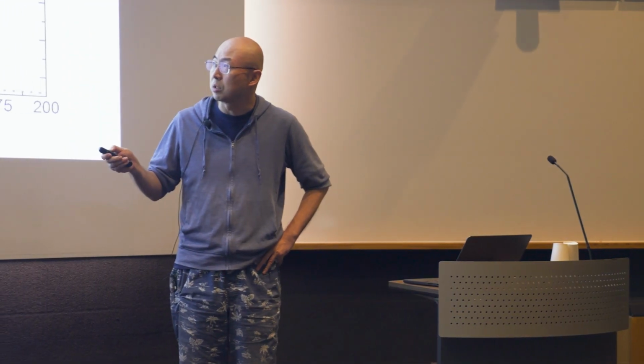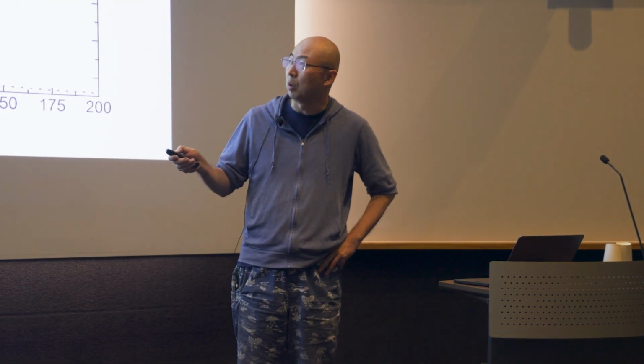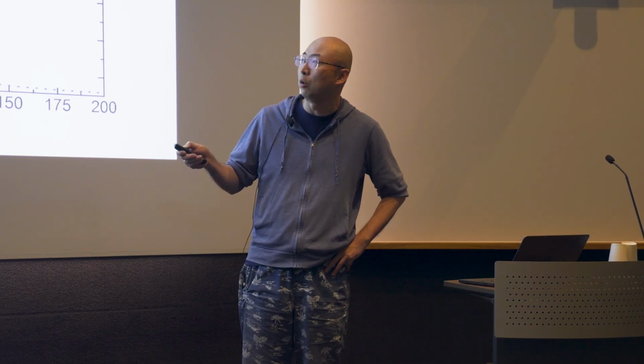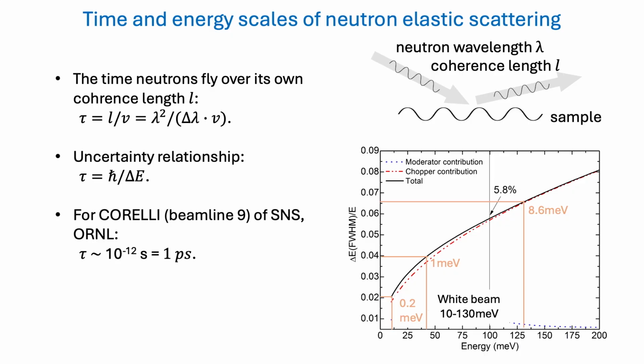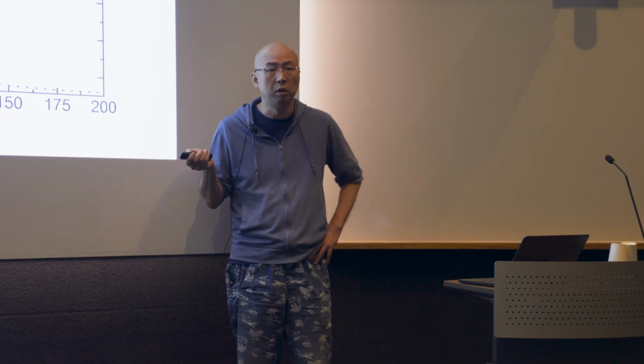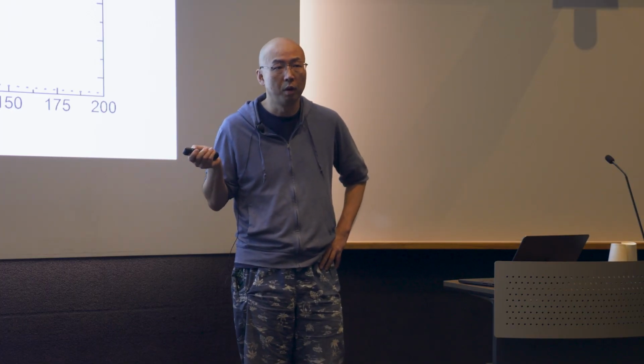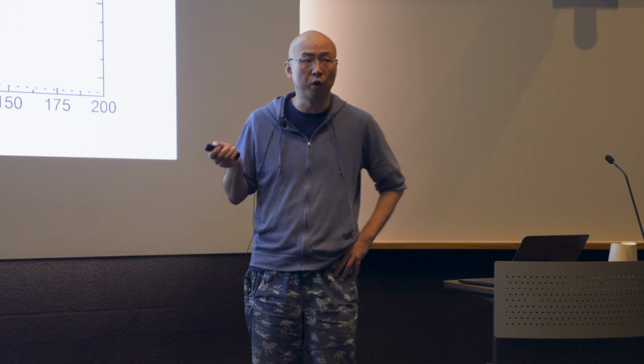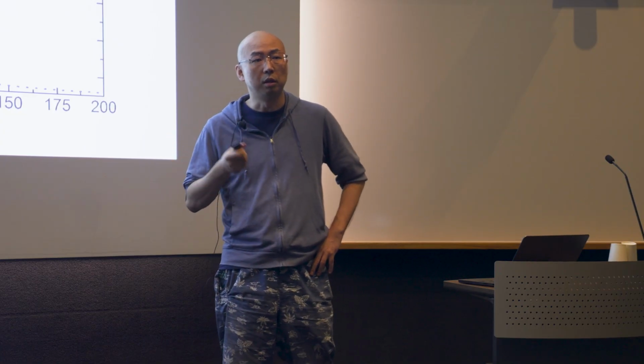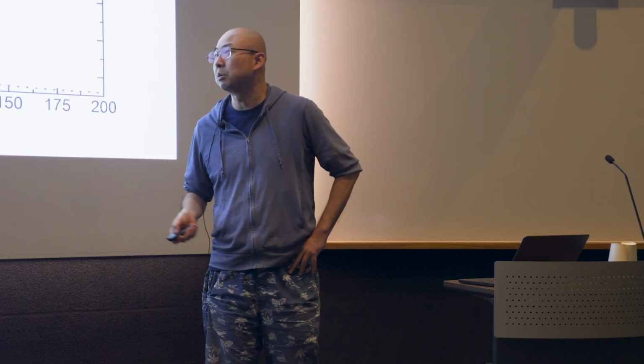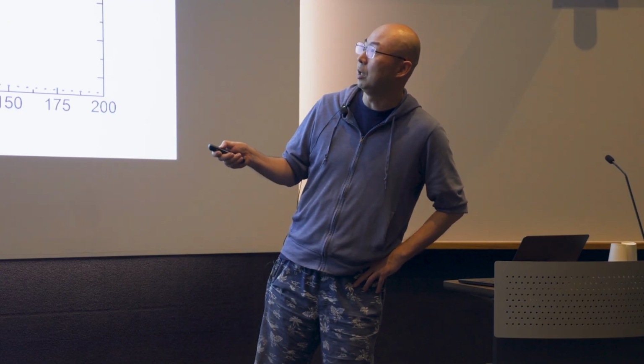So it has a coherence length L and it has a speed. And for the neutron to fly over its coherence length distance, you have the time scale lambda. So that's the observation time of a neutron to the spin ensemble. So if your sample is fluctuating too fast, shorter than the time constant here, the neutron sees the average. It will not register any signal. If your sample is static over this time scale, then you would observe spin correlations.